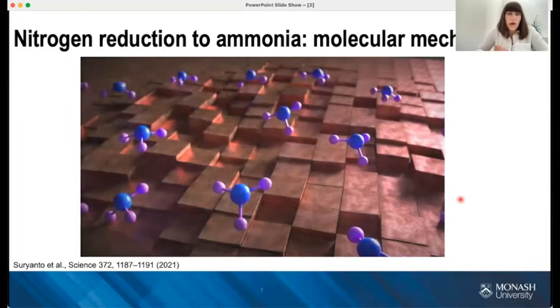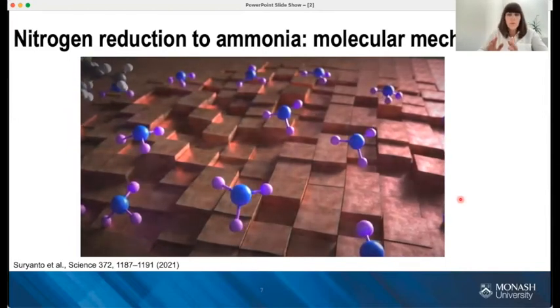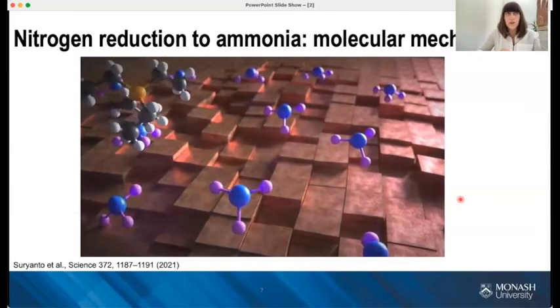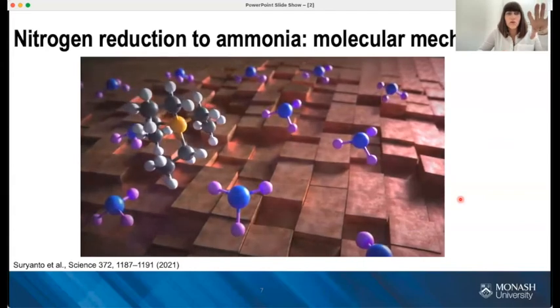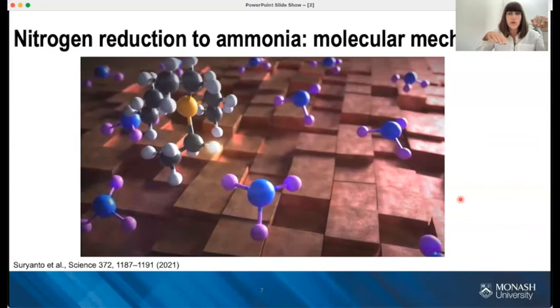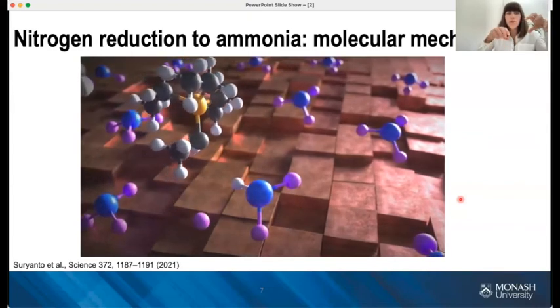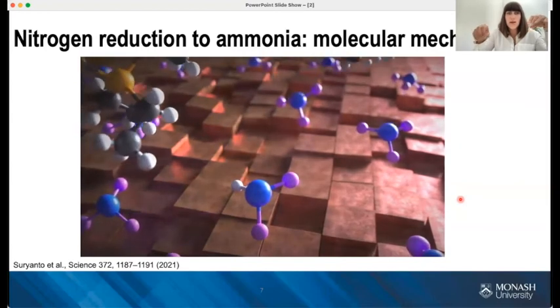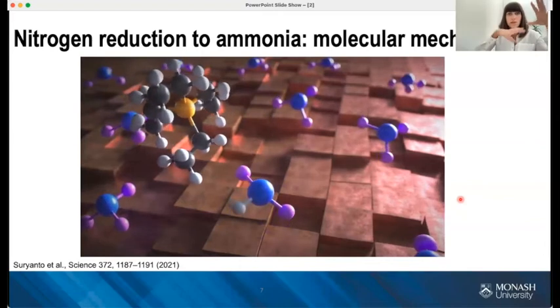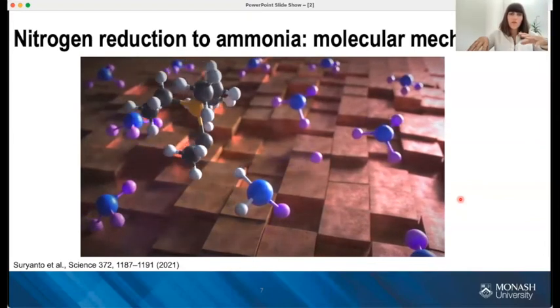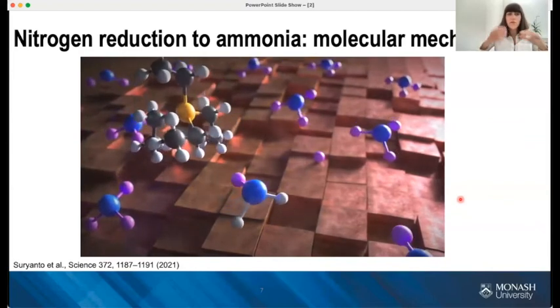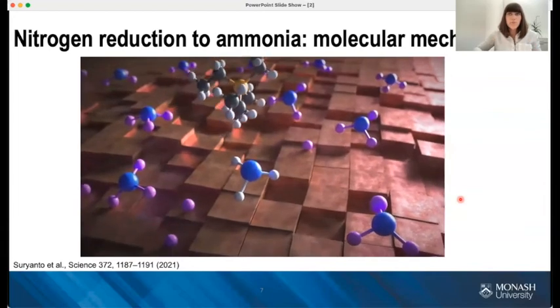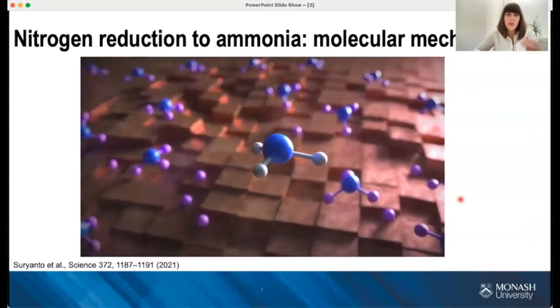Okay, so how does this process look at the molecular level? In the first step, the phosphonium cation, which you can see here, comes to the negative working electrode. And the negative working electrode is covered with lithium nitride. So when the phosphonium molecule reaches the surface, it releases one of its protons to the lithium nitride and becomes an ylide compound and diffuses away. Then it clears the surface for the next phosphonium to come that gives the proton, and so on. Three steps like this are required to produce an ammonia molecule. And in the end, positively charged lithium ions remain near the surface and are ready to form more lithium nitride. And again, the process is repeated. So this is how it works at the molecular level.